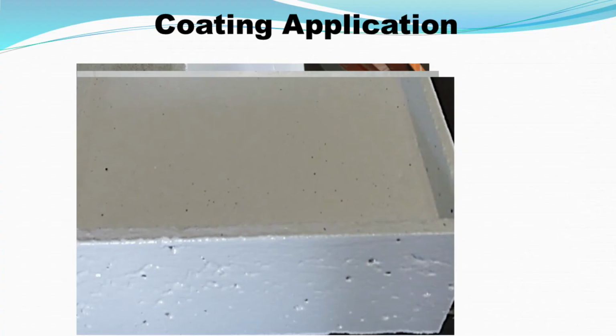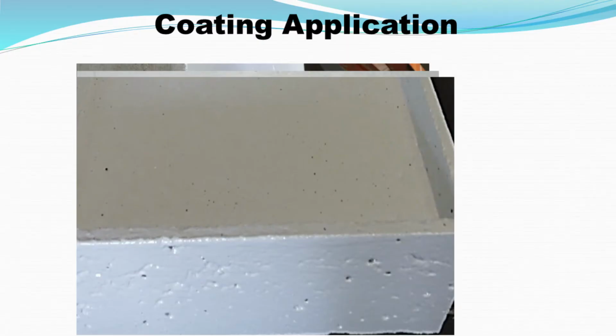In the laboratory, this is a picture of the concrete block specimen for the 90-day salt ponding testing. As you can see, the bug holes. The assumption was made that this would more closely resemble real life, that the coating application was not 100% pinhole free, because we didn't expect that contractors or maintenance forces were going to achieve 100% coating coverage, that the films were not going to be pinhole free simply because of the porosity and the texture of the substrate